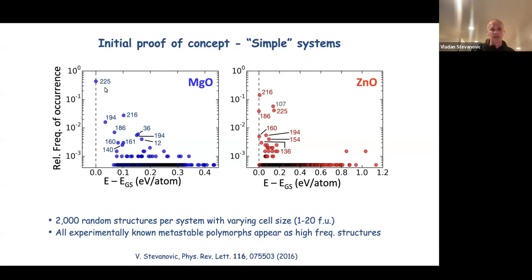So space group 225 is the rock salt, 194 is, I believe, the nickel arsenide one, 216 is zinc blende, 186 wurtzite, and so on. And in both of these pictures, what you can, I think, very easily recognize is that at the top of the y-axis, you have, in the case of magnesium oxide, just one structure that occurs around 50% of the time. So the y-axis is a logarithmic scale, 50% of the time. And then after that, we have different other structures that occur, I don't know, 2% or less. This thick line here are the structure types that occur only once. Many of them are just low symmetry ones.